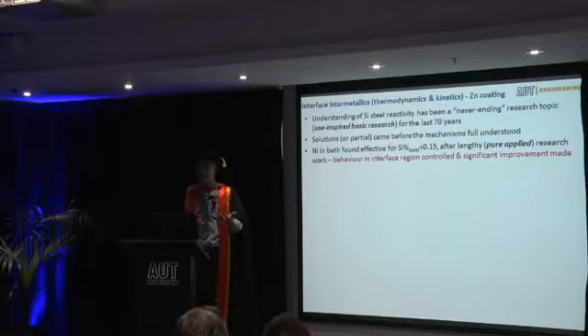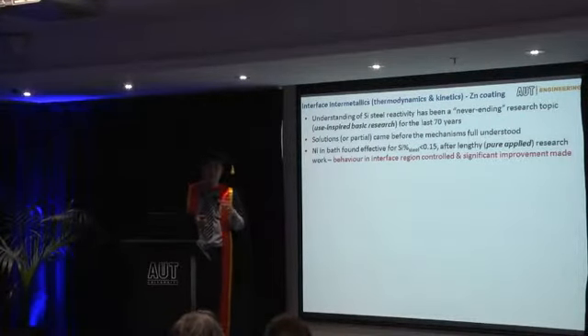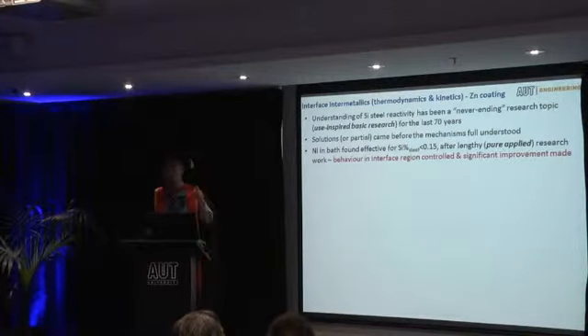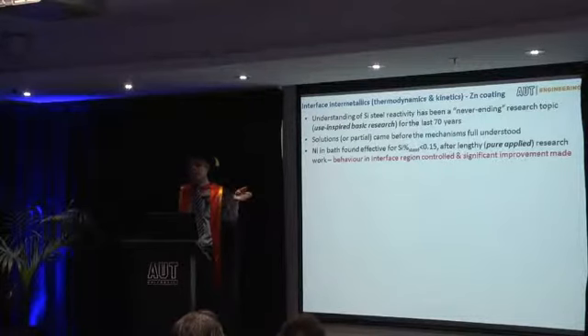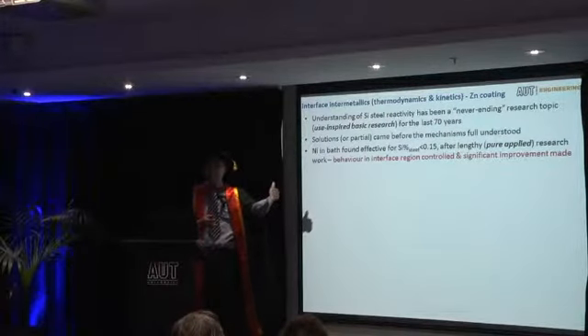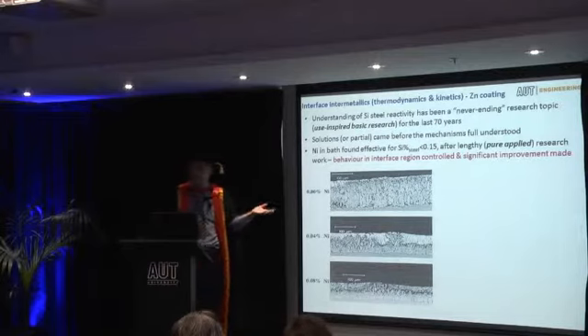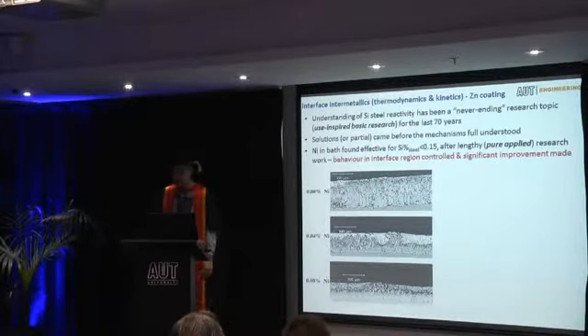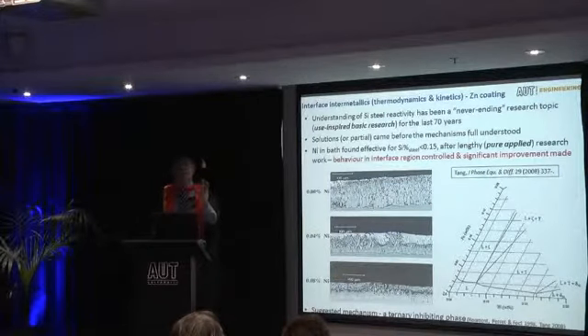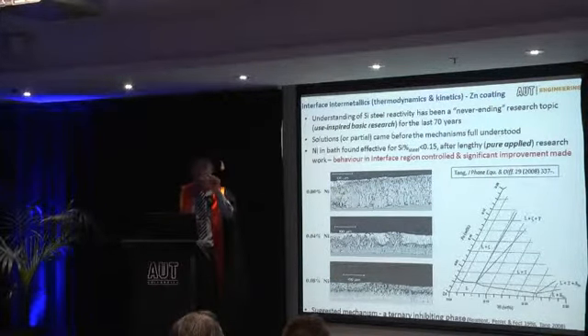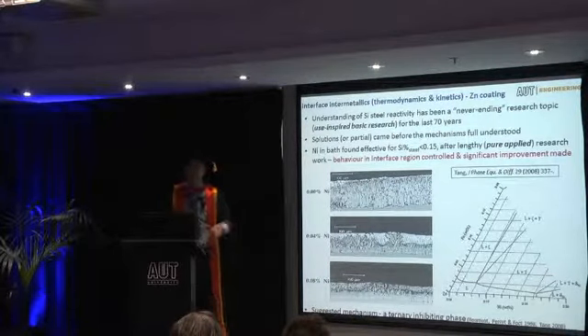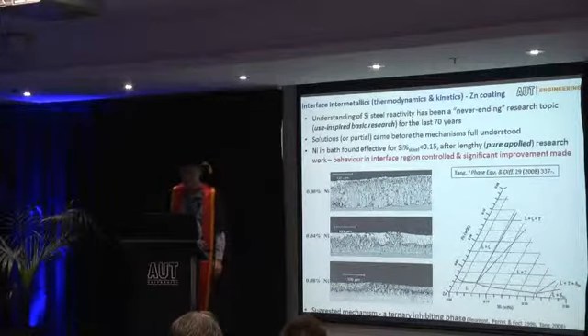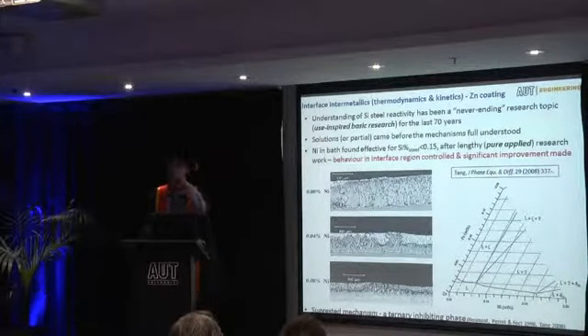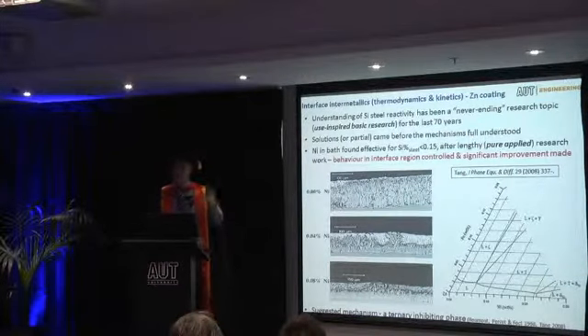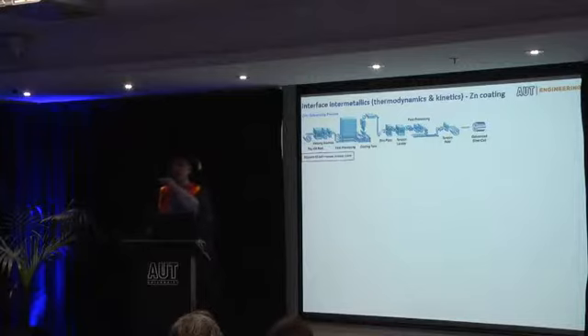Now, solutions or partial solutions actually came quite often before the mechanisms were fully understood, and nickel is one of those. After a long time of applied research, people figured out that if you put nickel in the bath, it can suppress those funny growths, and that's one of the examples you can see. And of course, from a thermodynamic point of view, people try to explain that it looks like an inhibiting ternary layer between the so-called bath and the layer.